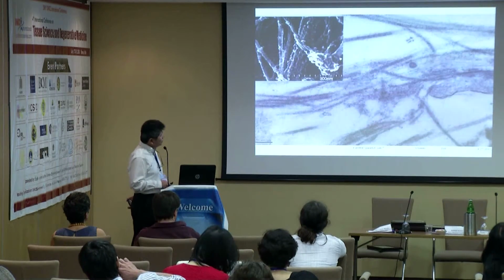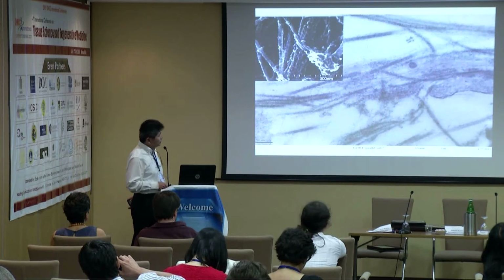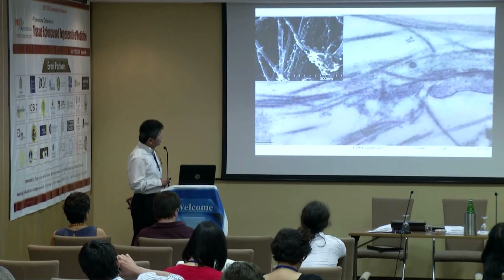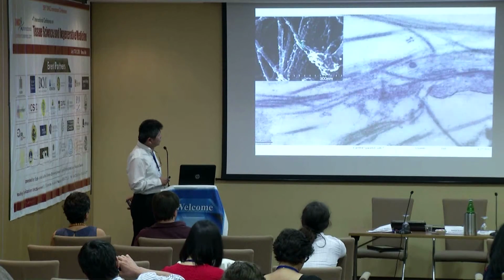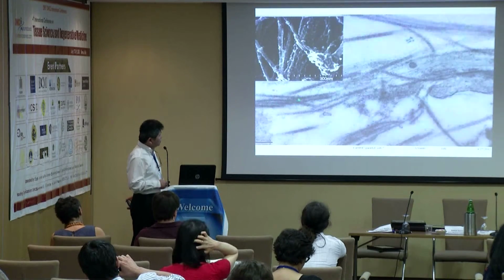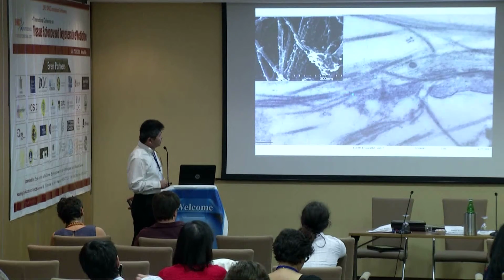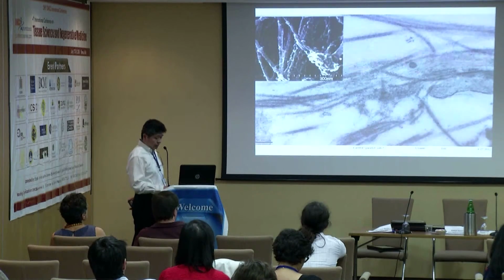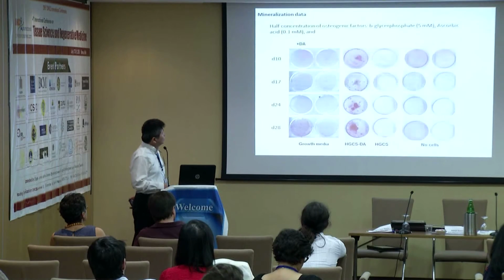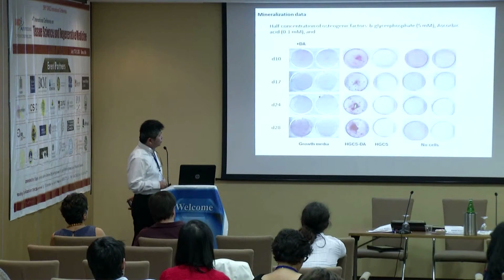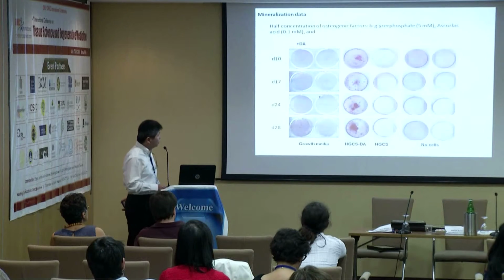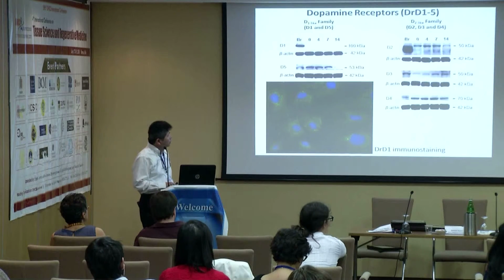And we further look at SEM and TEM to confirm those nodules. So basically, in the SEM, you can see the nodule on the surface of collagen fibers, and in TEM, you can see the D band disappear and be deposited by the mineral crystals. And also in the MSC data, we can show that when we add the dopamine into it, it starts to form the nodule, or bone mineral nodule. Without dopamine, it becomes very slow.